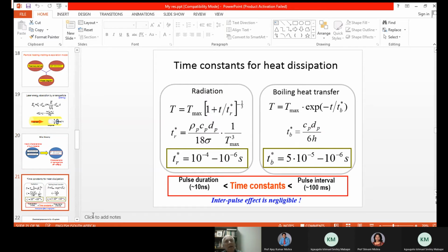Okay, here is a very important part of our theory. We calculate and estimate the energy dissipation time in two main processes: radiation heat loss and boiling heat transfer. Because the particle is put in the liquid, if the particle temperature becomes very high, the liquid around the particle will boil, and we always have heat transfer between the boiling liquid and the nanoparticle. Due to the heat transfer, the energy moves from the particle to the liquid. And first, there is the simple radiation process. If the particle temperature becomes so high, it radiates the energy.